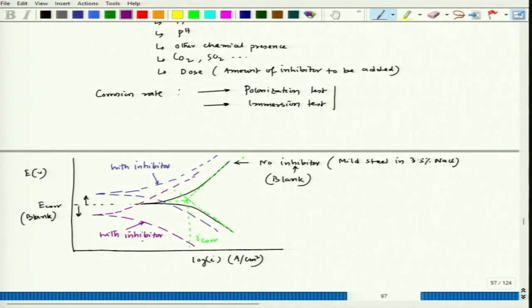Fine. Now, that time we can again calculate the corrosion rate by doing Tafel extrapolation. So, linear portion, here also the linear portion. Okay. Now, this will be the corrosion rate, inhibited. Okay. Now, in the case of the other curve, here also you can do Tafel extrapolation. Now, this is I corr inhibited.